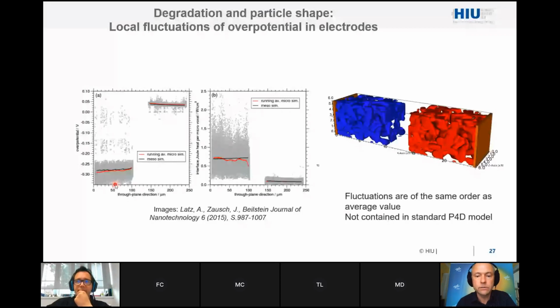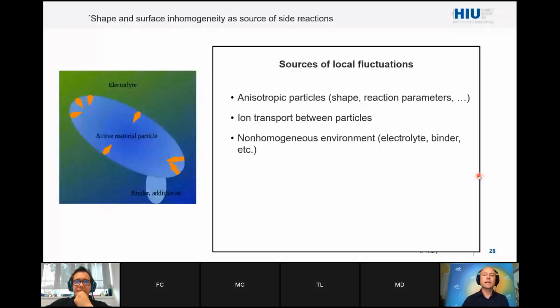So with Igor Traskunov, my PhD student, we did a very careful homogenization ansatz, a very careful analysis of what was done in the literature. And then we came up with the following idea, which we transformed into a rigorous mathematical upscaling procedure. Namely, the shape of the particle is a very key factor. Not only the shape of the particle, also inhomogeneous binder covering will produce overpotential fluctuation in the same order as the average. And they cannot be discarded if you want to predict the plating events or any other degradation phenomena.